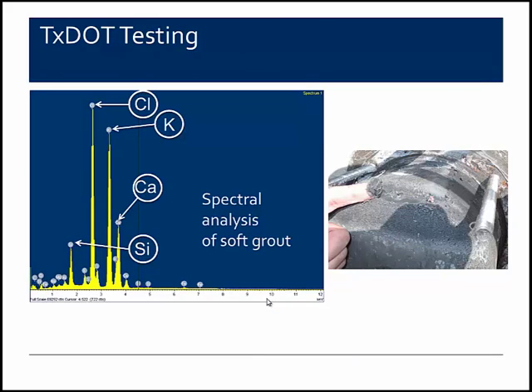The left slide shows a spectral analysis of that soft grout, and I'm not a concrete or cement chemist, but the folks that are tell me that this signature, if you will, of that chemistry of that material is not at all what you would expect from normally hydrated, properly mixed cementitious materials. You can see the very high chlorides, the extremely high potassium, that's the letter K, relative to the lower calcium and silicon, which should be higher in this. And then the picture on the right shows you just how easily that material can be removed and how soft it can be.